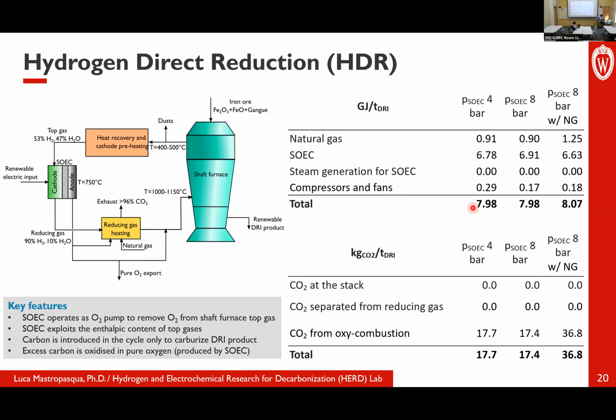On the right-hand side, you see the energy and emission performance of this system. So we looked at, of course, many different configurations, but if you just look at the one on the left-hand side, the primary energy consumption of this process is around 8 gigajoule per ton of DRI. And if you compare it with the number that I told you at the beginning, the conventional blast furnace case consumes around 20 gigajoule per ton of steel. So we are reducing the primary energy consumption by more than half.